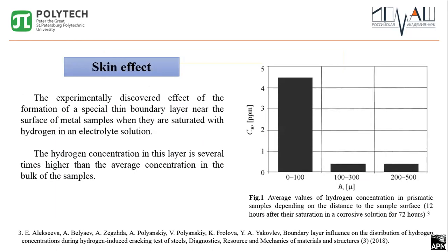At the same time, charging with hydrogen leads to a strong inhomogeneity of the distribution of hydrogen concentration. As a result of that, the concentration of hydrogen in a surface layer with a thickness of the order of one size of the metal grain is tens of times higher than the concentration inside the sample. This phenomenon is called the skin effect, and so far it has not been considered in modeling hydrogen diffusion and